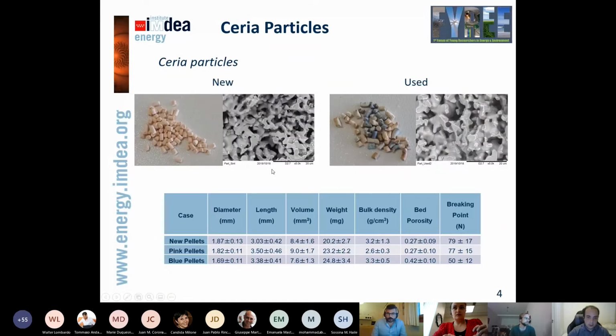This bed is composed of ceria particles that are more or less 2 millimeters in diameter and 3 millimeters long. Those particles were developed by the Institute of Catalysis and Petrochemistry from CSIC. And you can see here the difference between these particles when we first introduce them into the reactor, and those that we take out after about 50 hours of use.